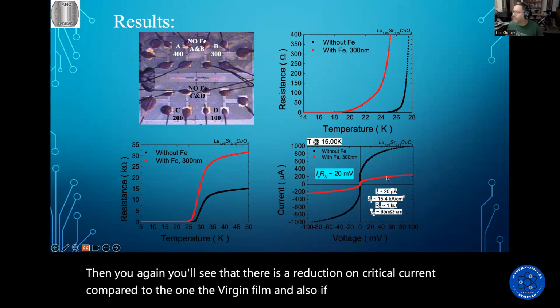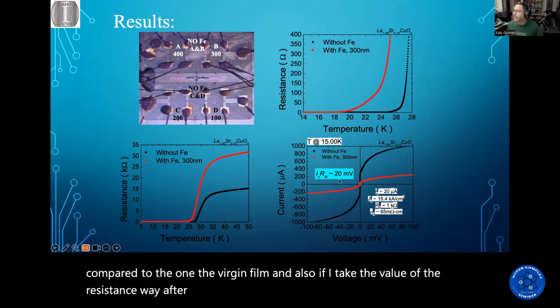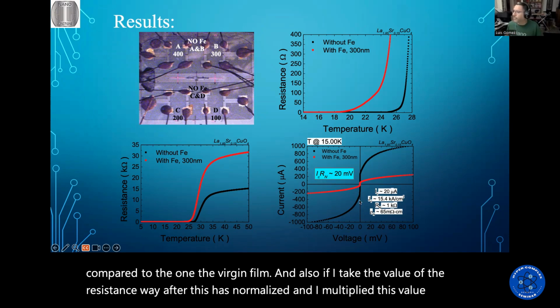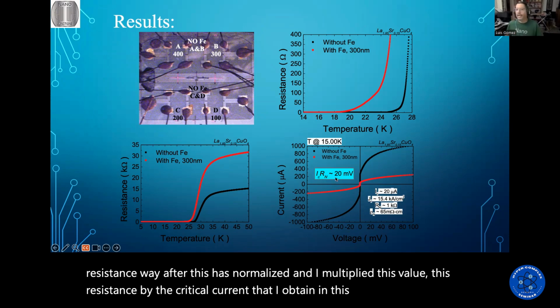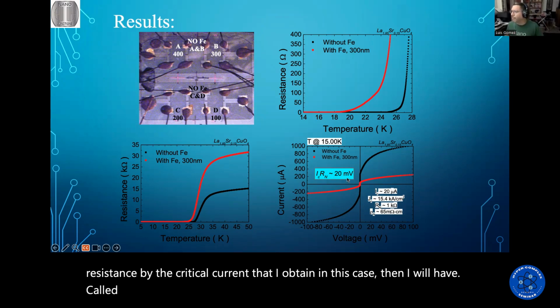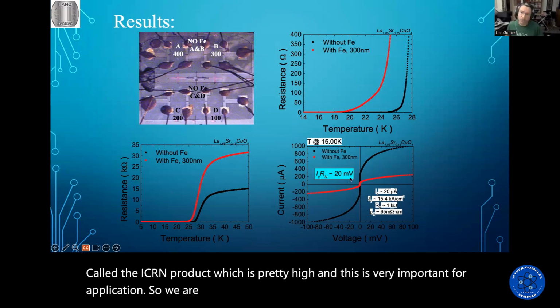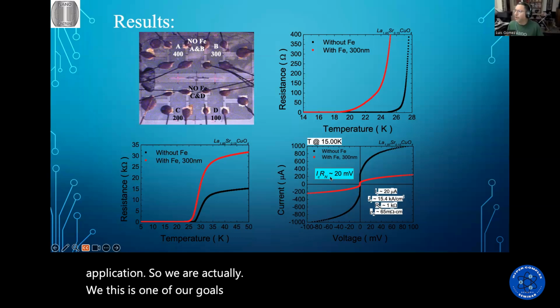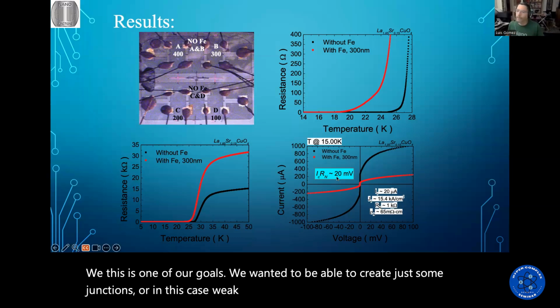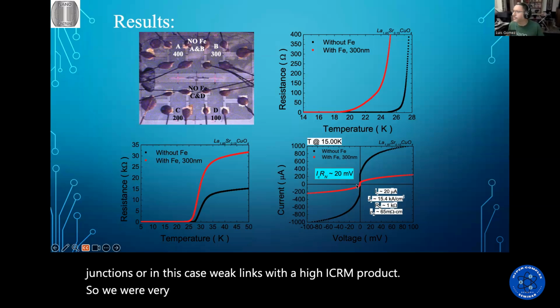And also, if I take the value of the resistance way after this has normalized, and I multiply this value of resistance by the critical current that I obtain in this case, then I would have what we call the ICRN product, which is pretty high, and this is very important for applications. So this is one of our goals. We wanted to be able to create Josephson junctions, or in this case, weak links, with a high ICRN product. So we were very excited at seeing this.